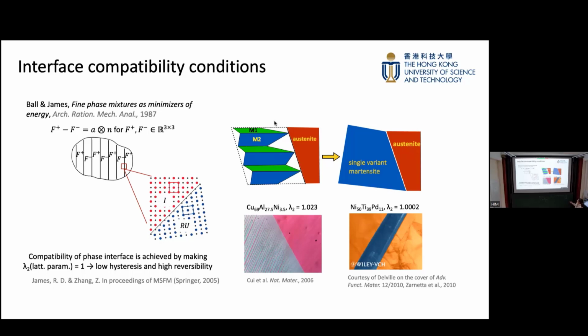So here, in some real materials, people measure the lattice parameters and calculate the equivalent value of the stretch tensor. That is U here. As we can see, this one is far away from one, and this one is quite close to one. And then we find this twin laminae here when it's not a perfect interface, and we have an elastic transition layer and martensite variant branching into the austenite. And this one is obviously different from that one. This is austenite, and they have a very big martensite single variant. So those are some results from 10 years ago.